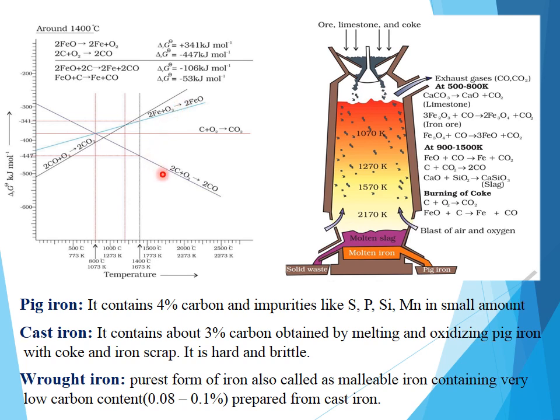Instead, we have two graphs which are lying below the iron oxide graph, that is carbon monoxide from carbon and carbon dioxide from carbon. When they are lying below the iron oxide graph, carbon, that is coke, can be used as a reducing agent above 1200 Kelvin. Hence we can conclude that in the metallurgy of iron, at low temperature of around 1000 to 1200 Kelvin, carbon monoxide can be used as a reducing agent, and at a temperature greater than 1073 Kelvin, coke or carbon can be used as a reducing agent.